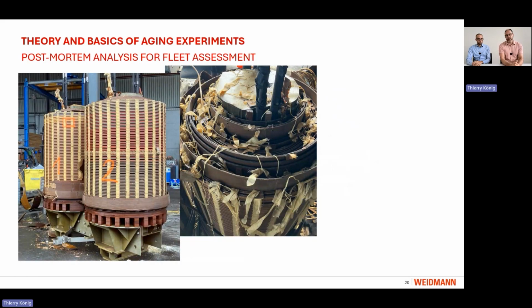This is a practical example of what you can do with these Arrhenius equations or the aging. Let's assume that you have a fleet of transformers, very similar transformers, and one of them broke down, so you have to dismantle it. What you can do is take samples here in the winding at different positions. You can measure the degree of polymerization and estimate the aging of your insulation.